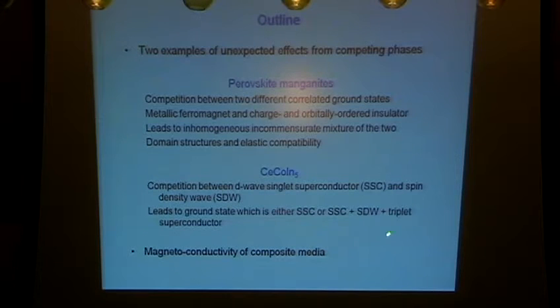And it turns out that these things can only exist if you have all of them, or you can just have one of them. And so you have a very strange phase diagram here where you have a magnet which appears only because the system is superconducting. Usually, magnetism and superconductivity don't like each other. But it seems here that there is an example, I'll argue that there is an example, of actually a system which is allowed to be an antiferromagnet because it's superconducting and not otherwise.